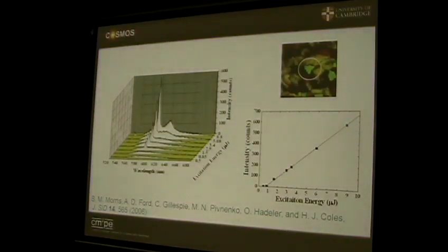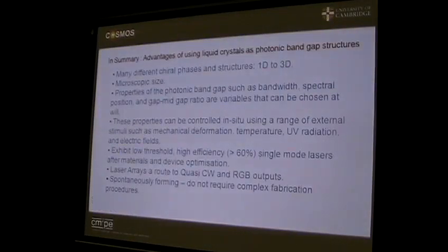But honestly and truly, the blue phase systems are very hard to make laser. You have to get exactly the right orientation. You have to think about what kind of dye you use, because is it a dye that goes into the host, or is it a dye that goes into the disclination line? And therefore, is it a long wavelength band or short wavelength band output?